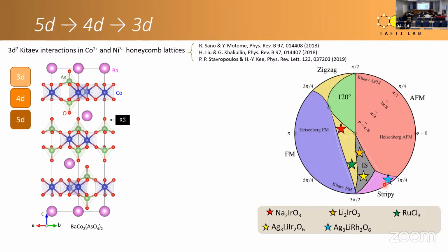And our interest in 3d transition metals came partly from some work that had already been done, especially on cobalt-based systems. So cobalt 2+ and nickel 3+ are in the 3d7 state. And in fact, theoretically, it's shown that there could also be Kitaev interactions in this 3d7 configuration. Of course, it's weaker because spin-orbit coupling is weaker. Previously people thought that 3d transition metals were not a good place to look for Kitaev physics. But there was some theoretical work originally by the group of Motome and later on by Khaliullin and others, who showed that indeed there could be Kitaev physics even in 3d transition metals.